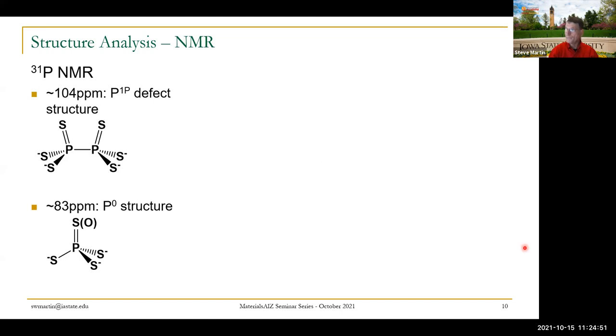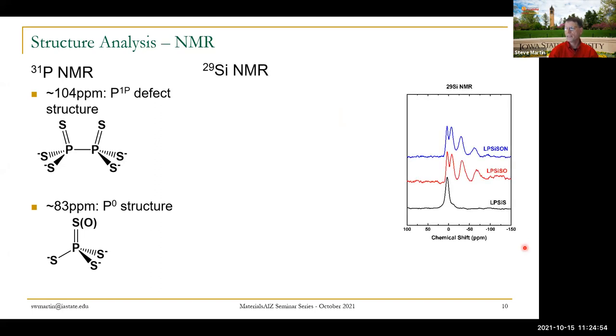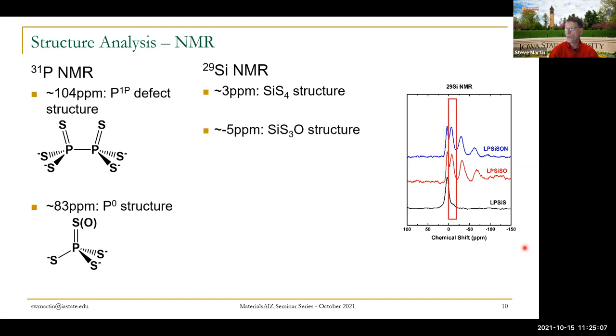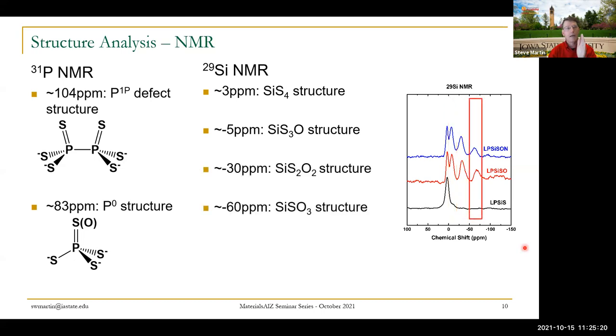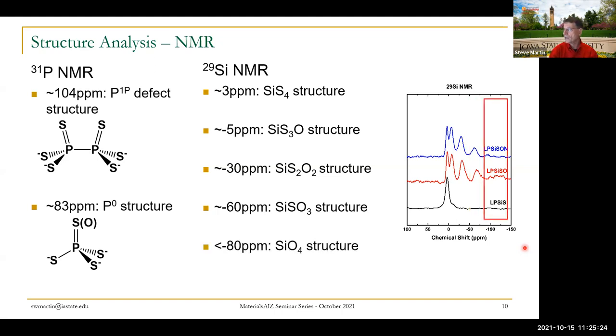And then going on to the silicon, remember the phosphorus takes the sulfur, the silicon takes the oxygen because of that more negative Gibbs free energy of formation of silicate structures. And you can see we have some silicon sulfide structures, but now we can clearly identify mixed oxysulfides. What you'll see is what you might expect. We have Si S3 with one oxygen, Si S2 with two oxygens, Si S1 with three oxygens. And then at the highest, most downfield shift, we have pure oxysilicates in these structures. I won't go into all the details today, but we can identify those as a function of composition and do a whole structural map.